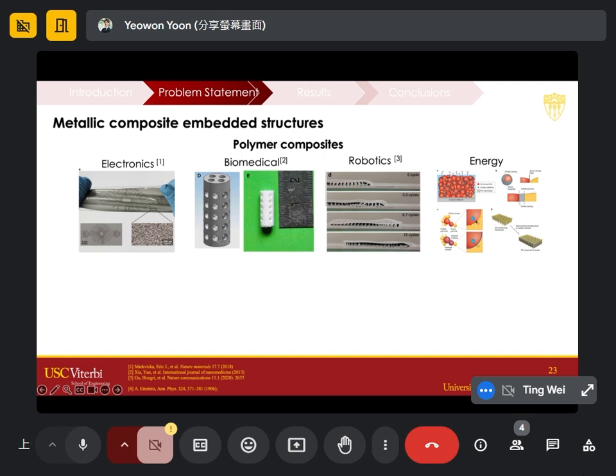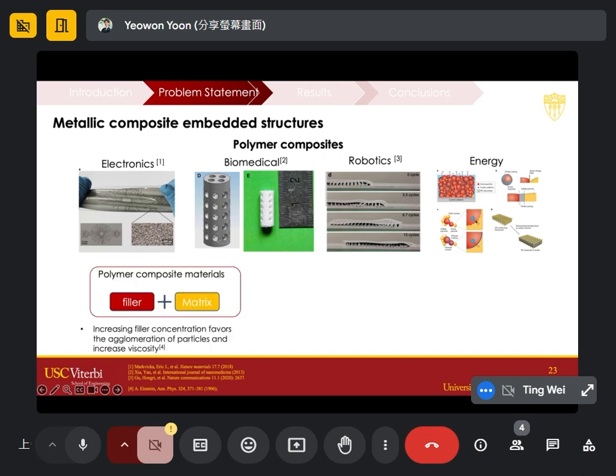All of these are called polymer composites in the sense that they have a mixture of two different materials. The filler material is in the red box, and the matrix is in the yellow box. The difference between the two is that the filler carries the functionality, and the matrix is the housing. The problem here is we want the maximum concentration to achieve maximum functionality, but there's a caveat, because increasing filler concentration makes the polymer composite extremely viscous because of the reduced Brownian motion. So the question is, how are we going to have the maximum functionality with a very high concentration, while still delivering structural matrix integrity, not to the point where it deflects and we reduce the functionality?